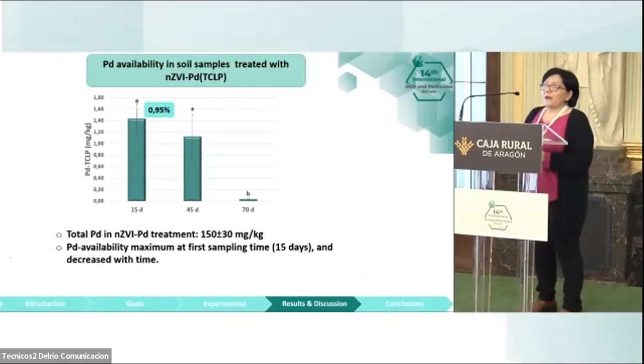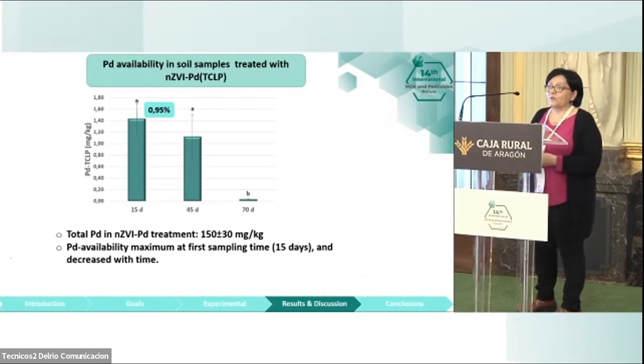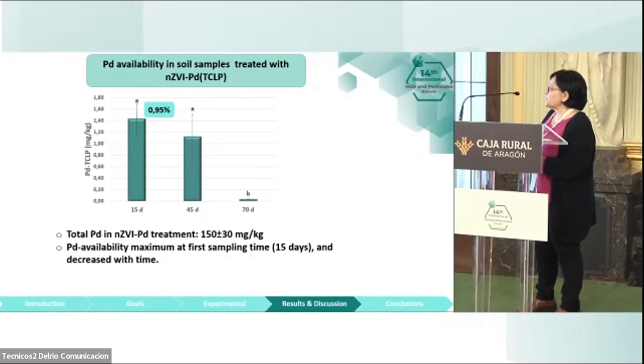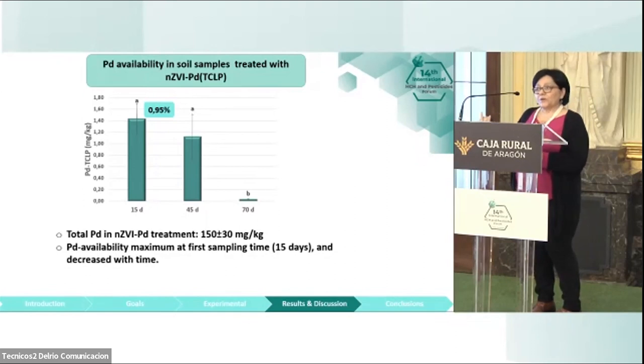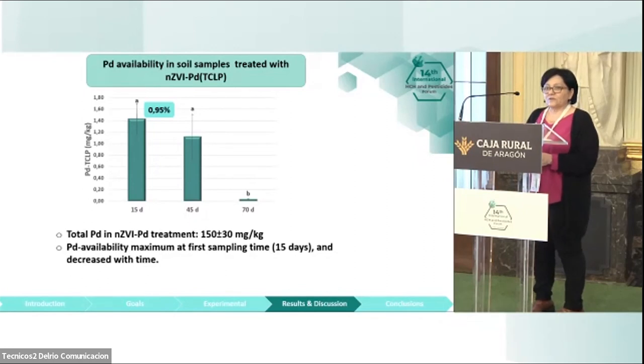Since we had palladium in the zero-valent iron particles, we had to analyze whether this palladium would be incorporated into the soil or not. According to the legislation, palladium is not regulated, but it is being used. So we wanted to know whether this was integrated or not. As you can see, with the same test, the TCLP, after 15 days we can see the concentration of palladium, but this gets reduced after 70 days. And the concentrations would be 1% of the solution applied. So yes, it is a low concentration, but we should take this into account when applying these kinds of nanoparticles.